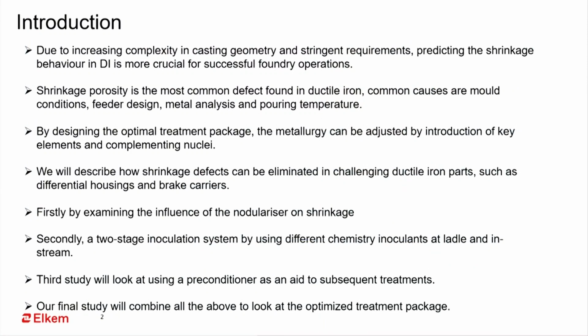The second case study is the 2 stage inoculation, not the same composition. It will be a different composition, but in 2 different stages. One is the ladle inoculation, another is the in-mold stream inoculation. The third case study is the effect of the preconditioner. Actually, when we are using raw material without any thermal analysis, it is difficult to measure the metal quality. By checking the chill, you can also check the metal quality. But with thermal analysis, before pouring the casting, you will get the metal quality conditions.